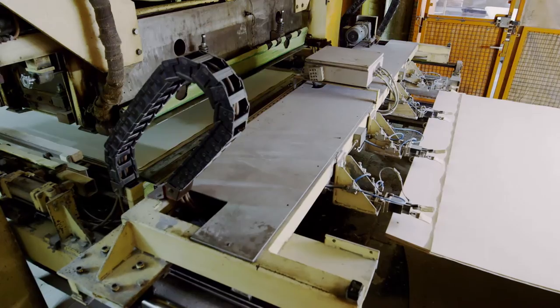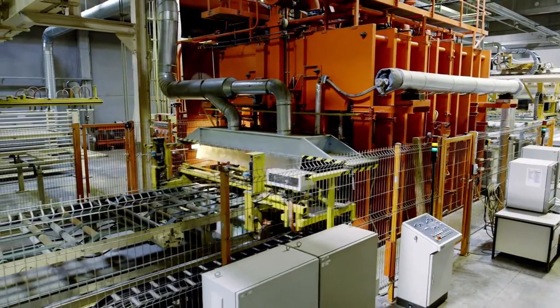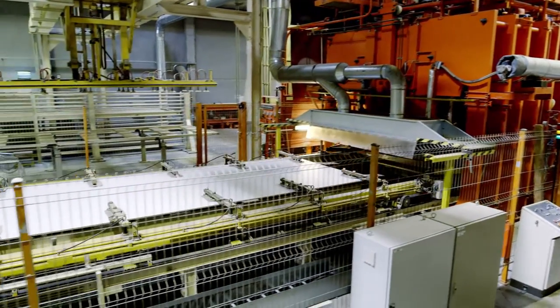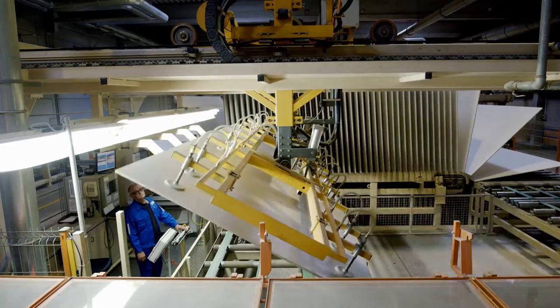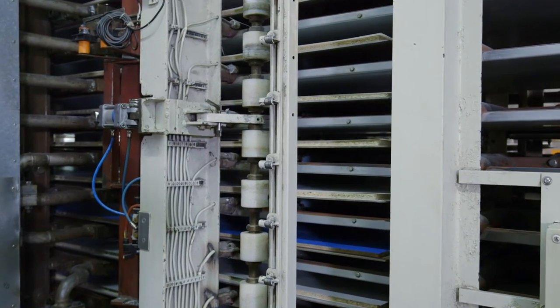Under heat and pressure, the resin in the film blends with the particle board. In a short-cycle press, this process performed at 180 degrees Celsius takes about 30 seconds depending on the decor and core material used.